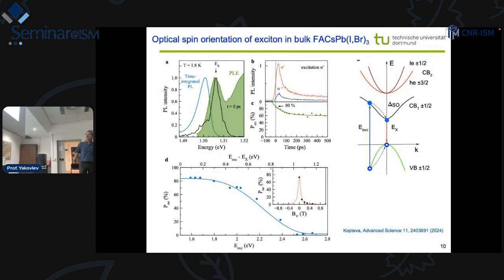How does it work for the perovskites? So again, we have this material close to FAPI. And now we focus on the excitons, the first 50 picosecond window. So on this emission, we excite with sigma plus polarization, and then we measure with time resolution the sigma plus component and the sigma minus component. And one can see here that the sigma plus component is much stronger than the sigma minus. If we calculate the polarization degree here, or the optical orientation degree, as it is called in this experiment, we reach 80%. And with time, this 80% decays only to 60% and then stays high. And the ultimate limit for the optical orientation is 100%. So we're very close to it.